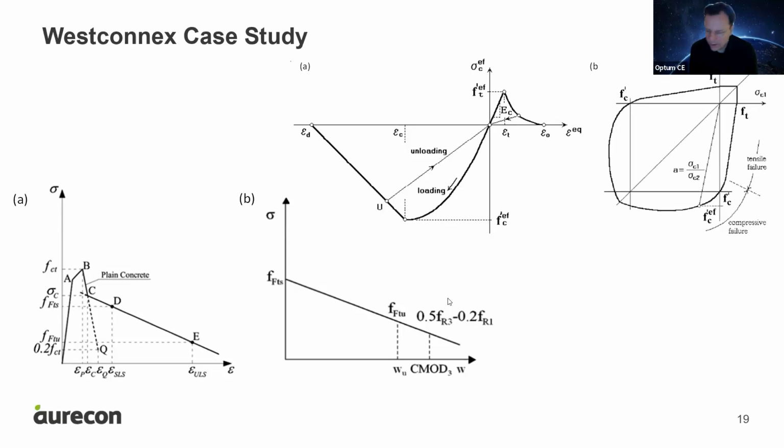Okay. Someone asked about fires. Yes, one of the main drivers for this design was actually fire. We do the same thing here. We do thermal modeling, and in some of the tools that we use, we have the thermal modeling and all the degradation effects that temperature has in reducing compressive strength, tensile strength, and modulus. This all comes in. It's a coupled analysis: we apply the thermal modeling, then we apply the load, and we see how the model behaves.